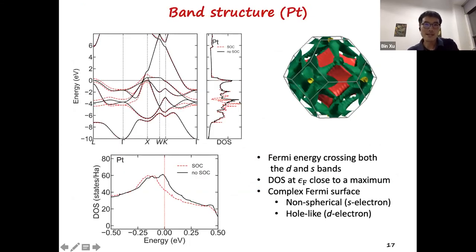Finally, let's look at platinum. Platinum has the Fermi level cross with both S-bands and d-bands. And its Fermi surface looks like this. The inside red surface, closed surface, is from the S-electron, which is highly distorted compared with the spherical shape. And the yellow and green colored are the d-band, the d-electron Fermi surface, which is a small electron pocket and a complex d-electron network.